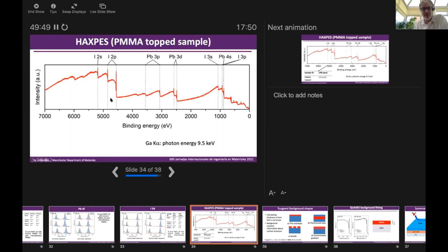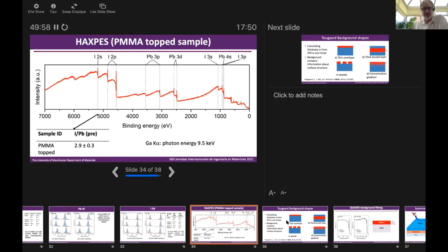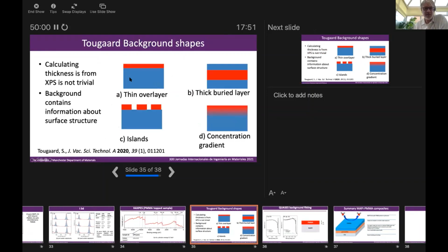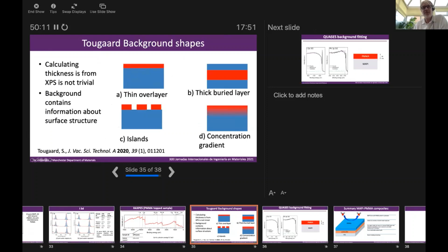We're also seeing deeper core levels here. As you probably all know, XPS is quite a useful tool in calculating the thickness of a film, but actually calculating the thickness of films isn't as trivial as it might sound, because we could have a hydrocarbon layer or polymer layer forming like this, which would give a particular signal, but we'd also get the same carbon to substrate ratio peaks if we had a much thicker layer buried as an interface, or if we had a thicker layer which was actually separated into islands. And so we need to know a little bit more about the structure of the overlayer in order to be sure that we're getting a continuous film.